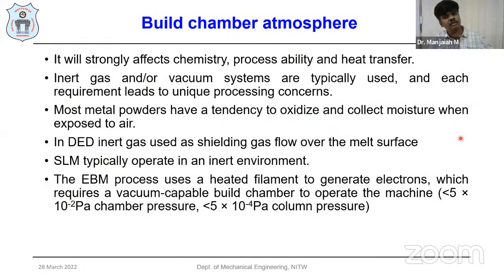And the other barriers are the build chamber atmosphere. It will strongly affect the chemistry, processability, as well as the heat transfer. Majorly, what kind of process chamber is required, whether for the SLM process, or for the DED process, or for the EBM process? We need to have inert gas or vacuum systems typically, which is required for the EBM process as well as for the SLM process. Most metal powders have a tendency to oxidize and collect moisture from the exposed air, especially titanium, which is very susceptible to oxidation, creating titanium oxide.